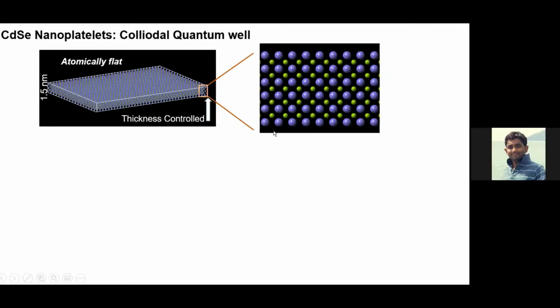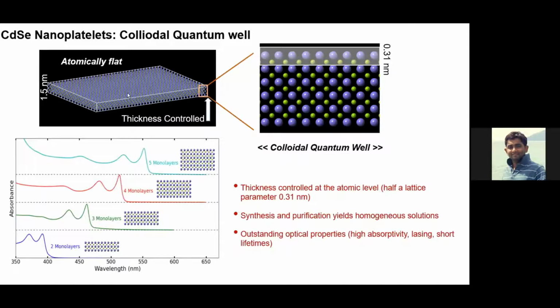Half a monolayer means one cadmium, one selenium. Here you can see one layer, two, three, four, five. So 5.5 means 5 monolayers. So you can distinguish the platelet by the confinement of the exciton. The electron can only be confined in one direction, while in the other two directions it flows freely, and the confinement is strong along the one dimension because it cannot move in this direction. That's why it behaves like a quantum well in a single system.